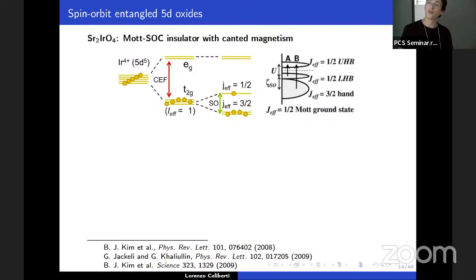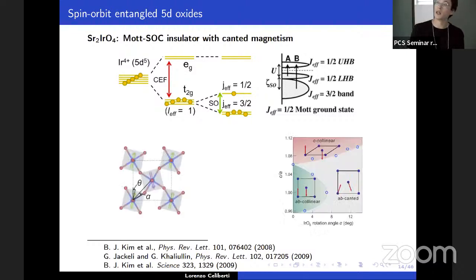Another effect of strong spin-orbit coupling, which is seen in this material, is the appearance of non-collinear magnetism. Non-collinear magnetism means that you have magnetic moments not aligned along the same direction, as you can see here, where the green arrows are at one angle and the blue ones at a different angle. This is usually not 90 degrees or 180 degrees, as in normal ferromagnets or antiferromagnets. And especially due to spin-orbit coupling, this is entangled with lattice degrees of freedom. So you can see here that you have different magnetic configurations depending on the geometrical parameters. You have this canting angle coming together with a rotation of the iridium-oxygen octahedron, characterized here by the angles theta and alpha.